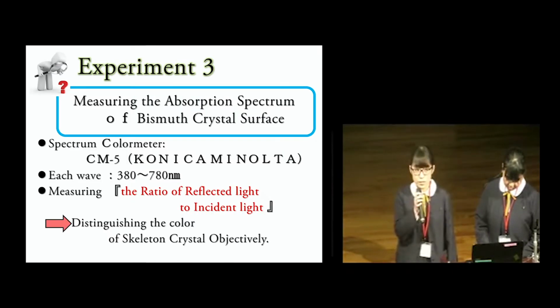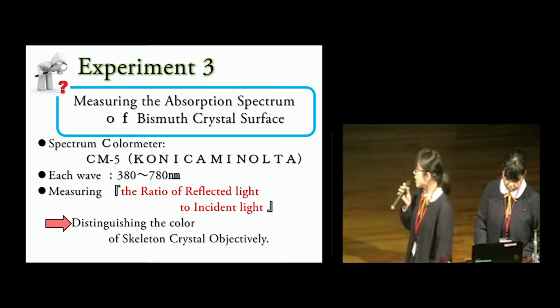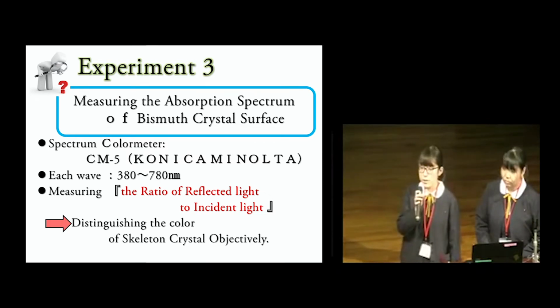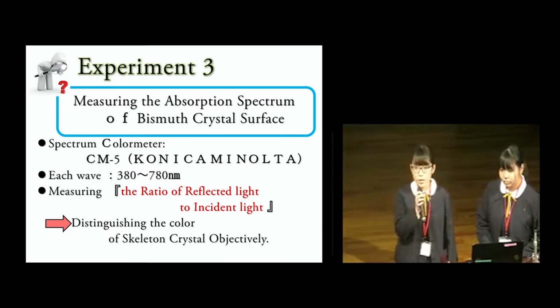We wanted to approach the process of bismuth crystals in experiment 2. We thought that the phenomenon of reflection and absorption of light when various wavelengths of light were applied to the crystal surface was related to the color of the crystal. Therefore, in experiment 3, we measured the absorption spectrum of the surface of bismuth crystals. We measured wavelengths from 380 to 780 nanometers on the surface with a spectral colorimeter, and we calculated the value of the reflected light with respect to the incident light. This number can objectively indicate the color of the crystal.